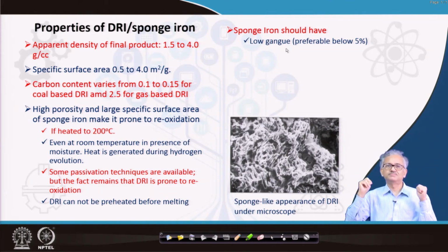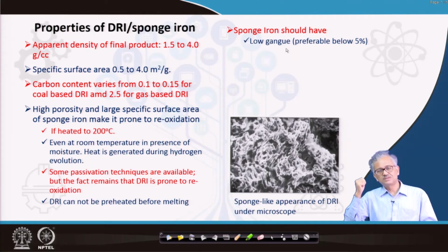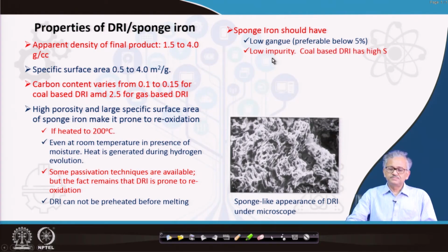Sponge iron should have low gangue. Gangue should not be very high. Metallization should be high, around 90% and above. Otherwise, a lot of iron will remain in the form of FeO, which increases the load on the electrical furnace. Besides, the gangue also has to be low. Gangue means the ore gangue like oxides, SiO2, P2O5, MnO, all these things. That means the starting raw material should be of high grade, with less gangue. And also the metallization should be high.